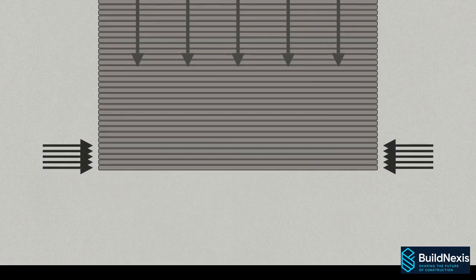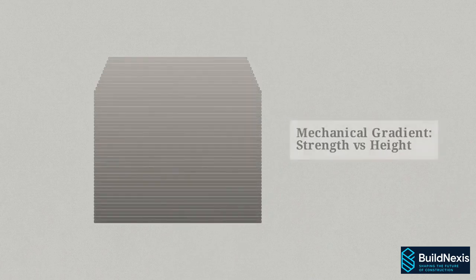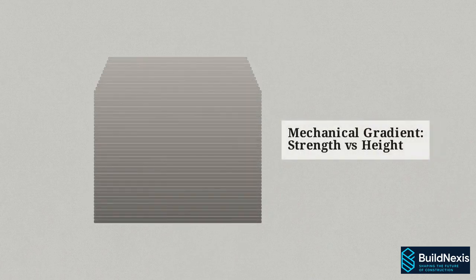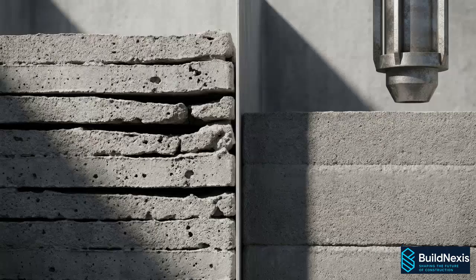The lower layers support the cumulative weight of the 99 layers stacked above them. That downward compressive force physically restricts the bottom layers, artificially limiting their shrinkage deformation. Elevation itself creates a mechanical gradient. Top layers are unweighted, shrink freely, and delaminate, while bottom layers are sealing into tight, monolithic bonds.